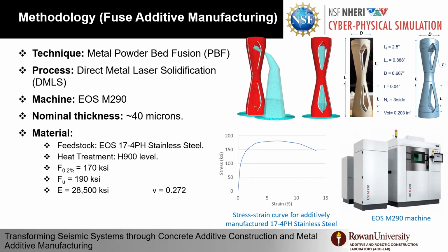Here is the stress-strain curve for the material that we use, especially for numerical simulation. So the yield stress at 0.2% is around 170,000 psi. Tensile ultimate strength is 190,000 psi. Modulus of elasticity is 28,500 ksi. And here I'm showing the specimen. The specimen height was only 2.5 inches, and the weight 50 grams. And the thickness of each plate was around 1 millimeter.